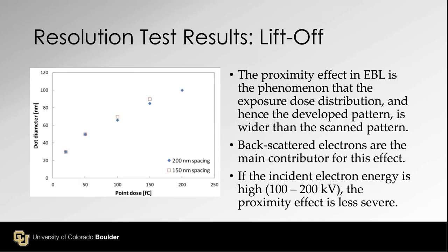As I decrease the point dose, I can reduce the dot diameter. The smallest one was a little less than 30 nanometers. These structures were made with my tungsten filament, ancient SEM. Nothing special, but by using electron beam lithography, I can make 30 nanometer dots without a very fancy e-beam lithography machine. The issue here with EBL is the proximity effect.